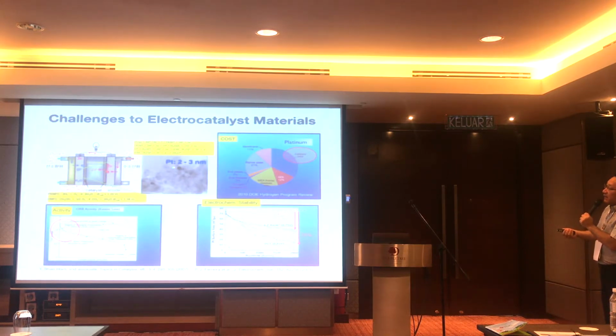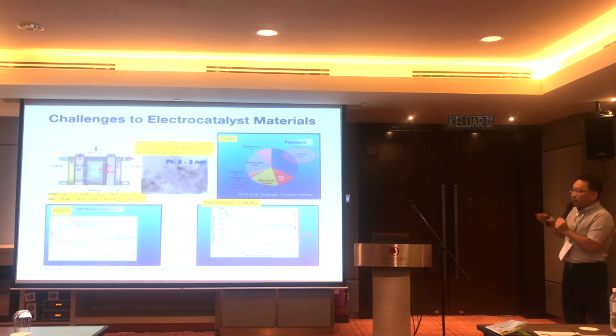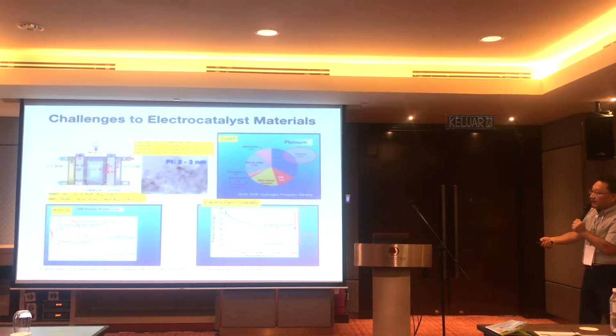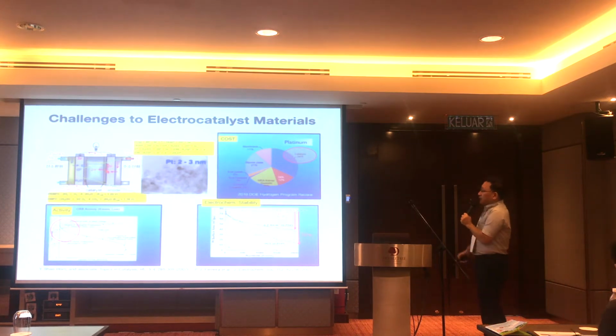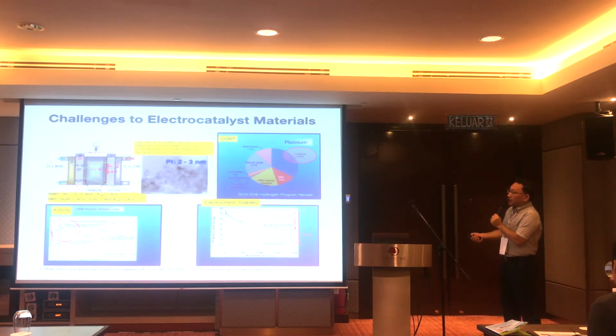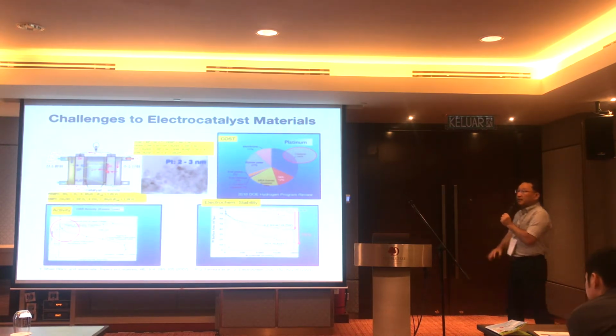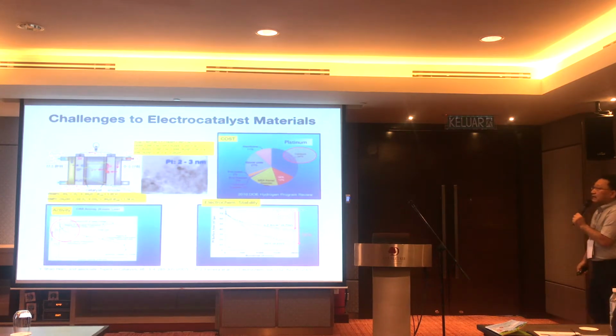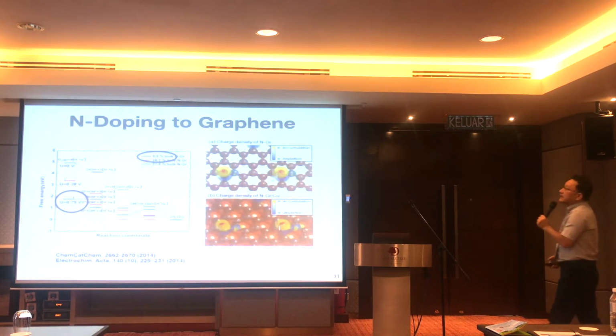So far, we found that platinum is the best material, but still the activity goes down very quickly when you push the gas. If you want to go faster, the activity goes down very quickly. So it is a problem again. Also, I told you about electrochemical stability issues in acidic solutions: platinum at this size regime dissolves at very low potential, so it just disappears. So cost, activity, and stability issues are the most challenging issues we are facing now.